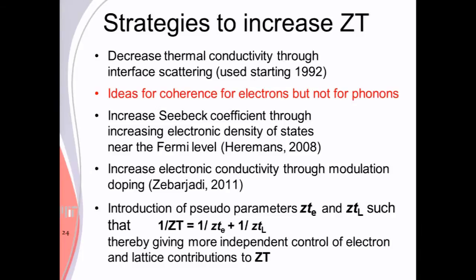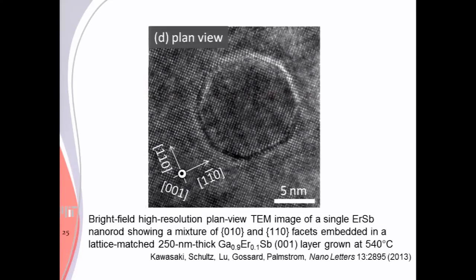Coherence was one idea: that for certain carriers, the system doesn't know you have a boundary. For example, this is some beautiful work done at Santa Barbara. This is a TEM picture. You have two different materials, with material X inside that circle and material Y outside. It doesn't matter so much what they are, but they have really different atoms. You can have some heavy atoms inside and lighter ones outside, so that you can scatter phonons much more effectively at the boundary. But the boundary doesn't show very much, so the phonons see it, but the electrons will be less sensitive.